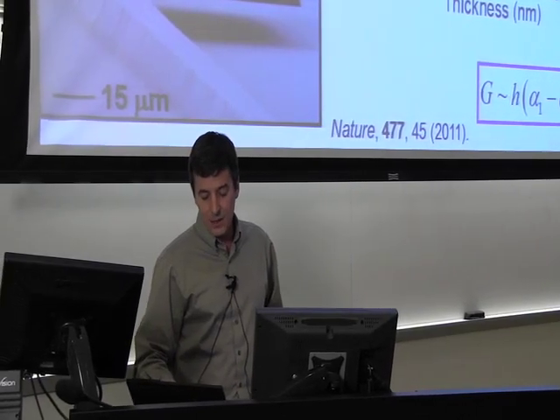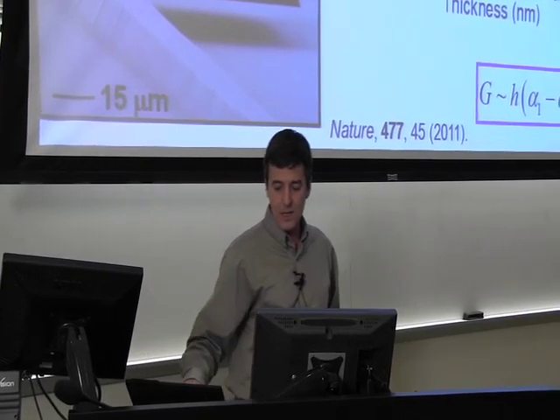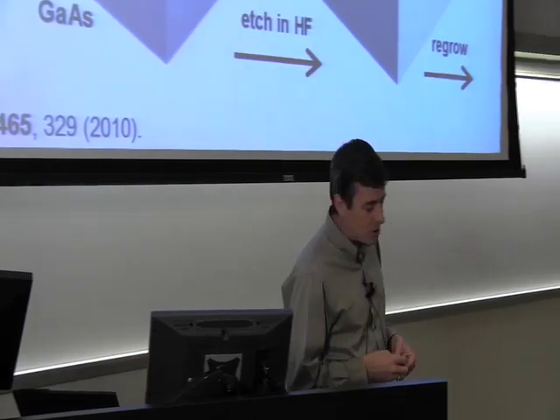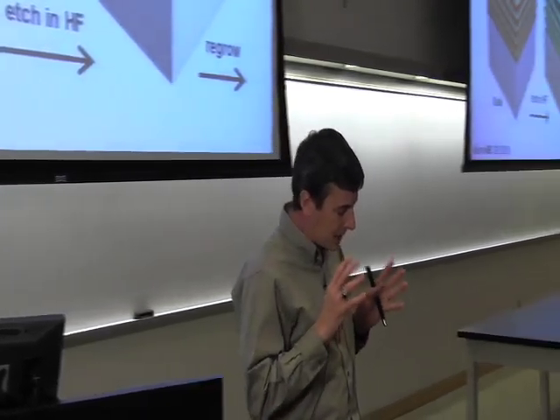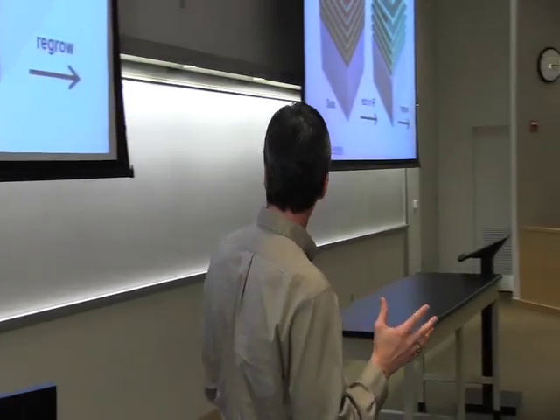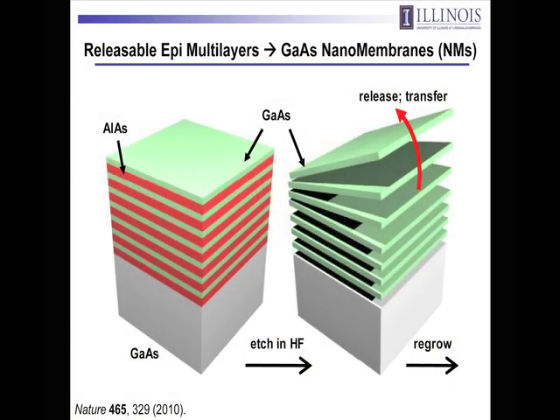How do you create materials like that in the first place? There's a variety of ways to do it. You can do it by anisotropically etching silicon wafers that have 1-1-1 orientation. You can also do it with compound semiconductors. I'll show you that second example in the next couple of slides, because materials like gallium arsenide are interesting if you want to do high-performance solar cells, a laser or an LED, or RF electronics. And so in this case, we use very advanced forms of epitaxial liftoff.